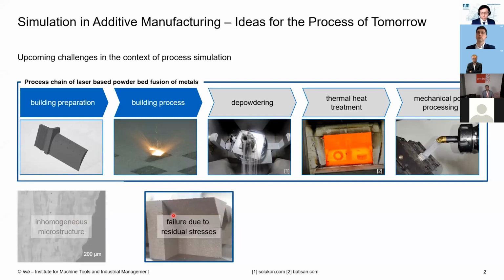Furthermore, we have also failure due to residual stresses. So parts cannot be used in further applications due to the high temperature gradients, which are then resulting in residual stresses. And also these residual stresses are mainly influenced by the building preparation, so how we select process parameters and where they are assigned. So for example, laser power, scan speed, and exposure patterns.